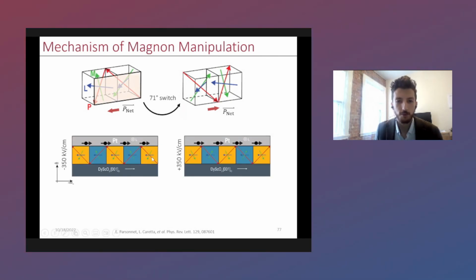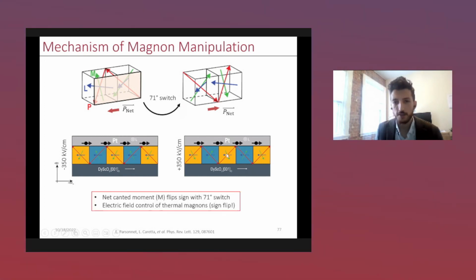What you'll find is that the polarization goes from right to left in one case, and the magnetization canted moment follows that. As we switch the polarization, the same thing: the polarization now goes from left to right, and the canted moment also goes from left to right. Thus, because the canted moment is switching, the spin polarization of the spin waves that transfer through the material are opposite, and thus you get different signals across the platinum electrode. So by controlling the polarization, and thus the canted moment, we can control the sign of the anomaly.